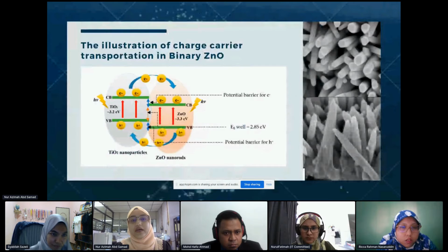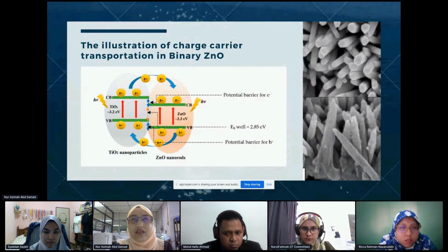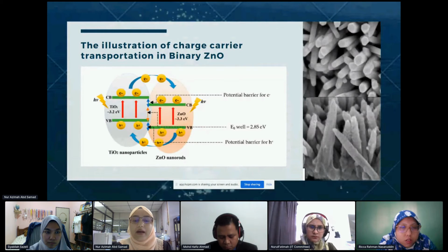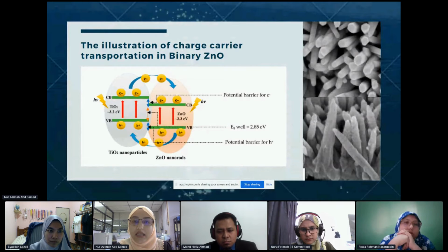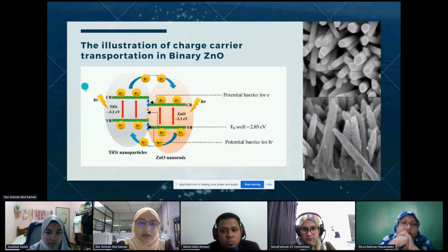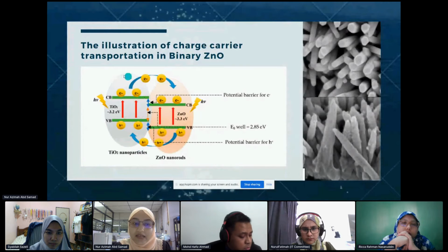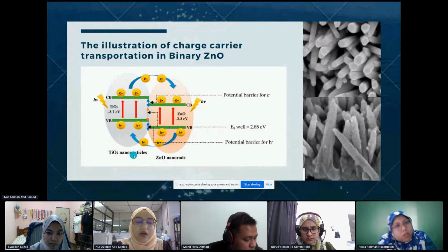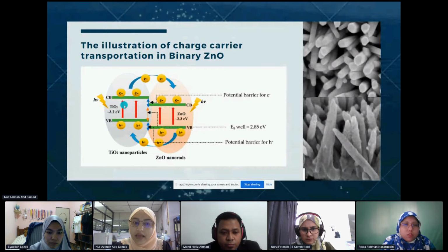After this, zinc oxide can be incorporated with metal. Recently in the 2010s, people incorporated it with titanium and palladium. But now, 2010 and above, people incorporate it with another semiconductor or make it ternary. Here we combine it with another semiconductor, which is titanium, and this one is zinc oxide. This is a heterojunction. If we combine it with metal, basically it will produce another Fermi level in the band gap. However, in this case, we create the heterojunction.